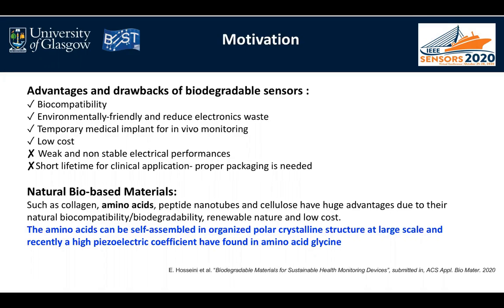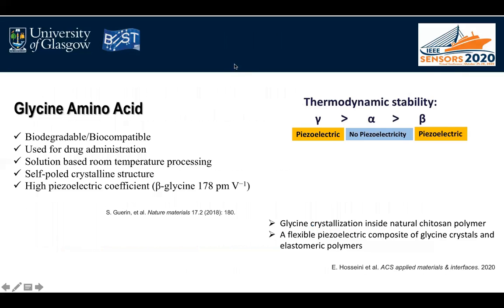but fabrication of biodegradable sensors from natural and bio-based materials such as amino acids, proteins, and polysaccharide-based polymers has huge advantages due to their natural biodegradability, renewable nature, and low cost. And here we used the amino acid glycine as an active layer to fabricate a biodegradable sensor, because amino acids can be self-assembled in an organized polar crystalline structure at large scale. Recently, a high piezoelectric coefficient has been found in glycine.